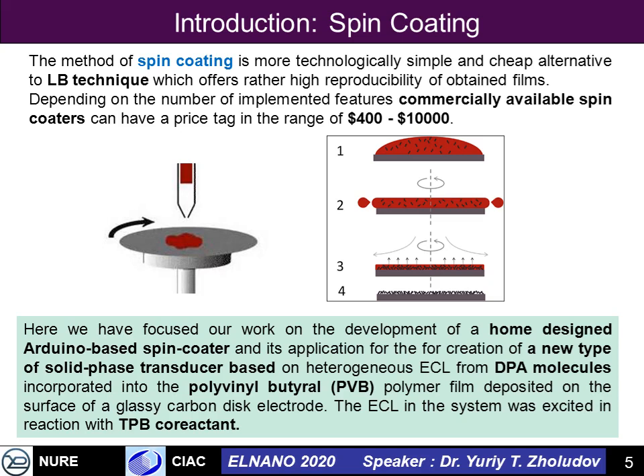So one of the goals of this part of the research was to develop a simple, cheap spin coating system which can be used for deposition of polymer films on the electrode surface. When we talk about spin coating, the method is based on a rotating electrode or substrate surface, which is spinning, and deposition or drop casting of a solution containing the required mixture of polymer, fluorophore, and other species. The solution is made in an organic solvent which evaporates, and when evaporation happens during the spinning, a uniform film is formed, as you can see in steps 1, 2, 3, 4 on the picture on the right.